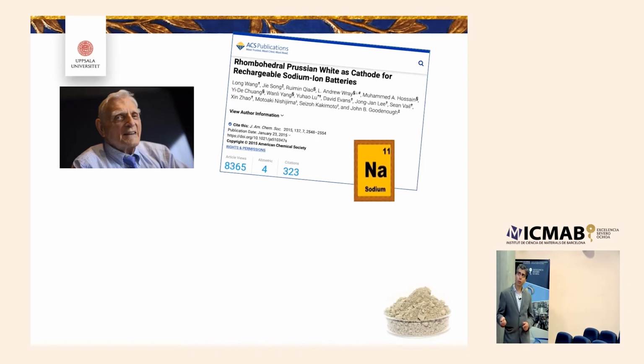But then we found that the synthesis was actually challenging. It was high temperature, high pressure synthesis that they showed. That motivated us to find an easier way, because we were lazy, to make this material.